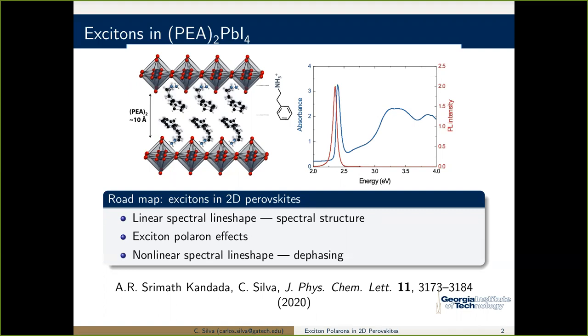And so this looks like a Wannier exciton, except that it's extremely strongly bound. This is comparable to what you find in 2D single layer transition metal dichalcogenides, where you have quantum and dielectric confinement that gives rise to exciton binding energies of the order of a few hundred millielectron volts. Here we are in the order of 300, 350 millielectron volts. And this is at room temperature. So very strongly excitonic behavior.